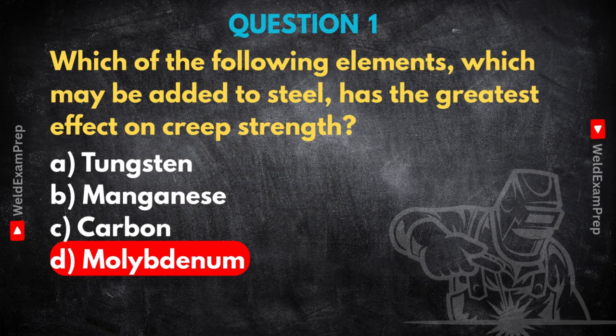Tungsten can help too, but molybdenum is particularly effective for creep resistance in many common steels. Manganese and carbon are essential for other steel properties, of course, but they don't have that same specific impact on resisting long-term creep like molybdenum does. Right. So for you listening, understanding this link between molybdenum and creep resistance is vital if you're inspecting or specifying materials for high-temp service. It's about safety and lifespan. That makes perfect sense. Engineering the material for the job.